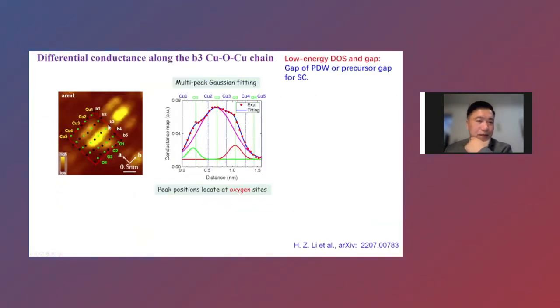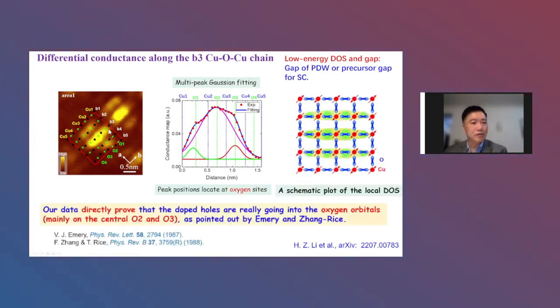Then we make a cut crossing this central bar. Then you will see that actually on the oxygen side, we see some kind of peak and knees, which means that the whole doping-induced density of states has some kind of maximum or knees near the oxygen, which strongly suggests that the holes are really doped to the oxygen side. So our data directly prove that the doped holes are really going into the oxygen orbitals, mainly the central oxygen 2 and oxygen 3, as pointed out by Emery and Zhang-Rice in the early studies, okay?